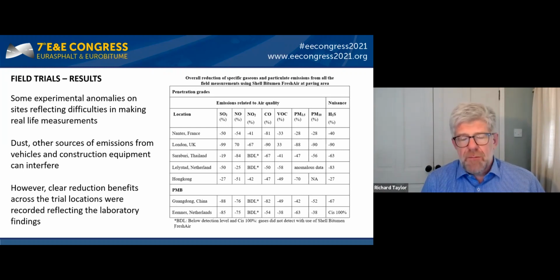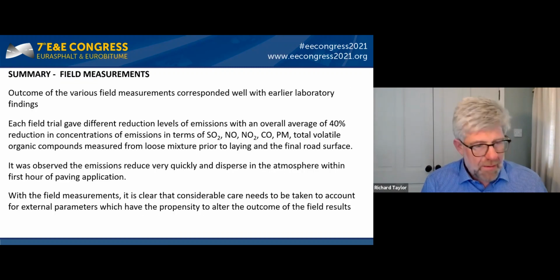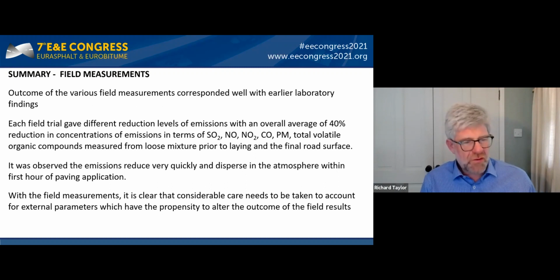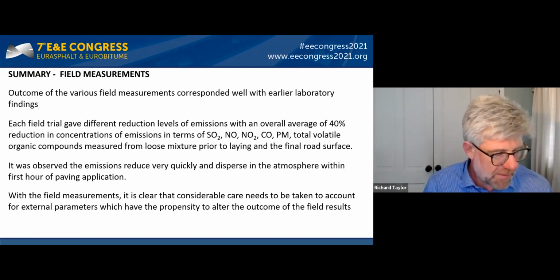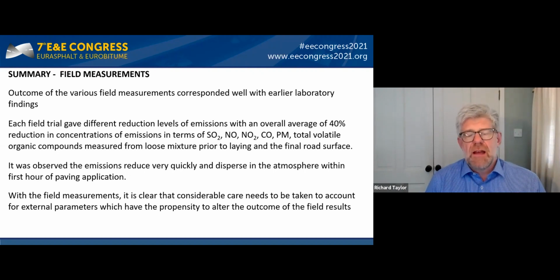But in general, if we look at this data as a data set, it's pretty clear that the additive is having a positive impact on the gas and the particulate emissions coming from the bitumen during the production of asphalt paving and the bitumen storage. And so if we look at the conclusion from the field trials, yes, there were issues with the measurements at times, which is to be expected. But in general, we feel that the outcome of the field trials was pretty well correlated with what we saw